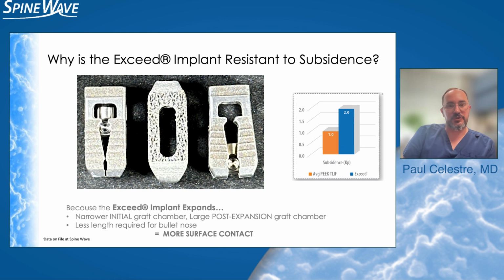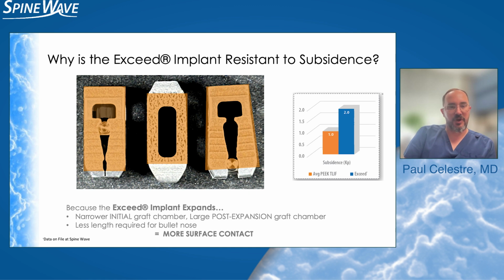This is likely related to two fundamental properties of the cage. First, the cage has a biplanar expansion. So if you look at the cage on the left, compared to a conventional TLIF cage, you'll see the absence of a graft chamber in the Exceed cage. However, after the cage has expanded in two different directions, as you'll see in a video in a moment, you have a large graft chamber that allows you to backfill the cage after cage expansion. This creates greater surface contact and also, in my opinion, creates greater ability to restore disc height. Furthermore, the surface technology allows for rapid integration of the cage into the end plates, and I have not seen any evidence of cage extrusion.